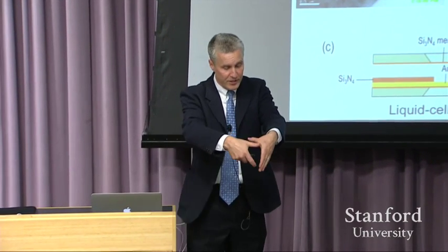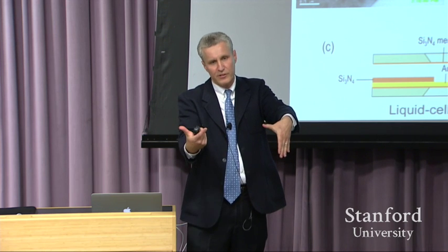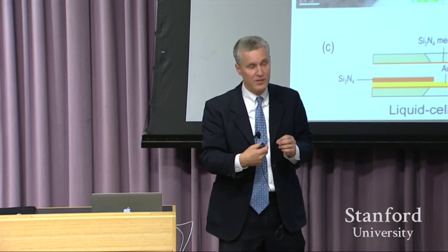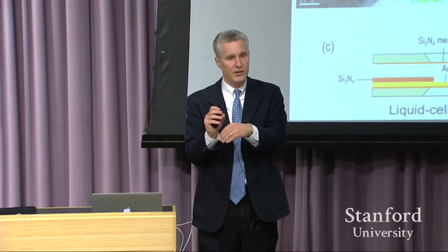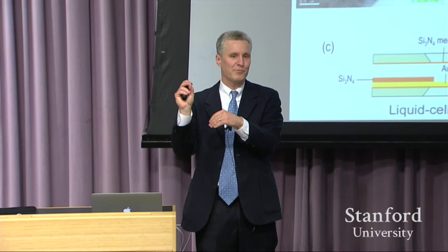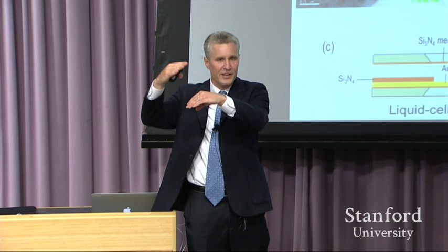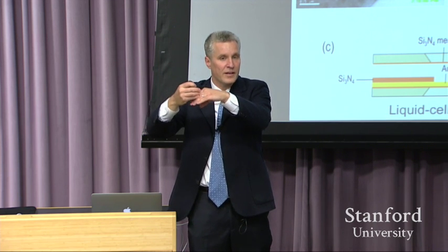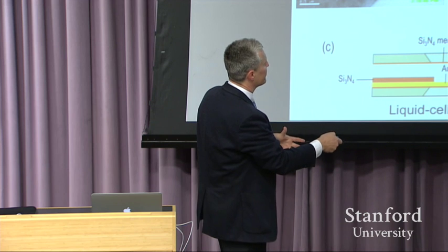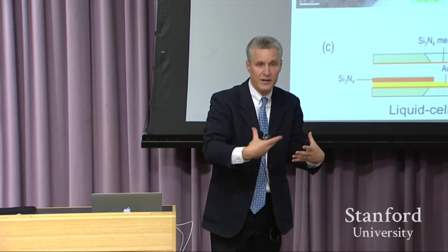And interestingly, the growth rate slows down like 1 over square root of time, which seems like a diffusive process, but what we think it is, and quantitatively there's good support for that, is this square root of time of diffusion of solvent molecules through the SEI layer. So as this film is growing, it keeps getting thicker, so it's passivating the surface, and eventually new solvent molecules can't get through. And so what happens is it starts growing like a hemisphere, but at some point the growth rate at the surface just gets way too slow, and you're demanding a higher current.